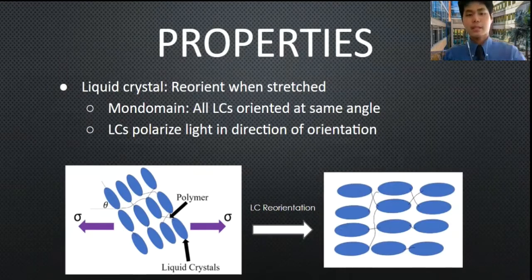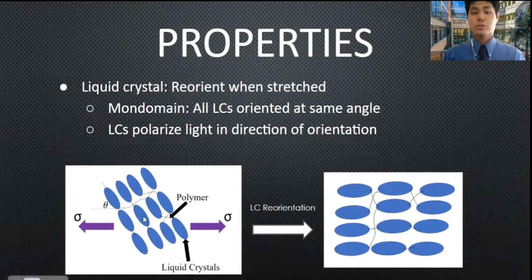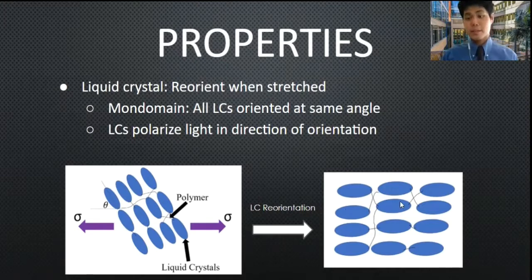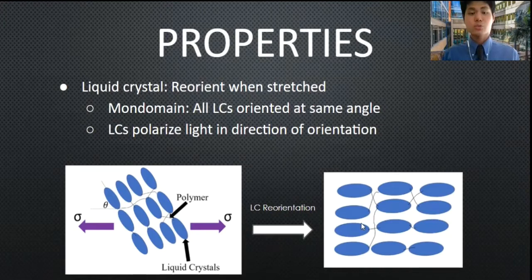Mainly, the liquid crystals come with interesting properties because they will reorient themselves in the direction of an incoming stress. For example, in monodomain LCEs — which is what we're working on in our research — the liquid crystals are all oriented in the same direction theta, as you can see on the picture on the bottom left. When you stretch this, all the liquid crystals reorient themselves until they're parallel with the force. From now on I'll refer to these as zero-degree LCEs for convenience. Another interesting property is that the liquid crystals will polarize light in the direction of orientation, which will be important when I discuss our experiments.